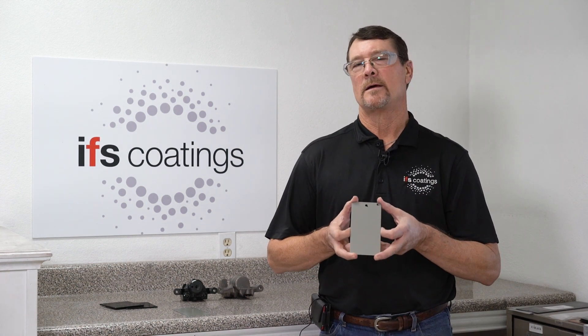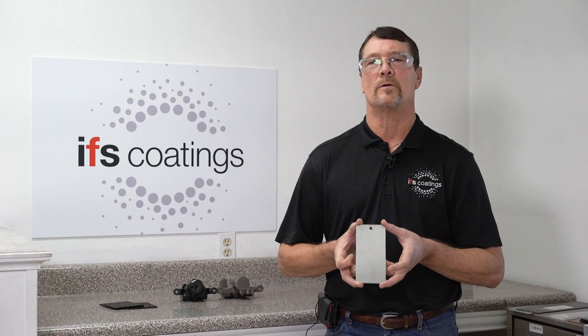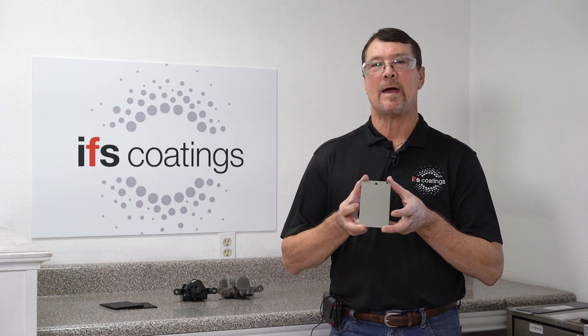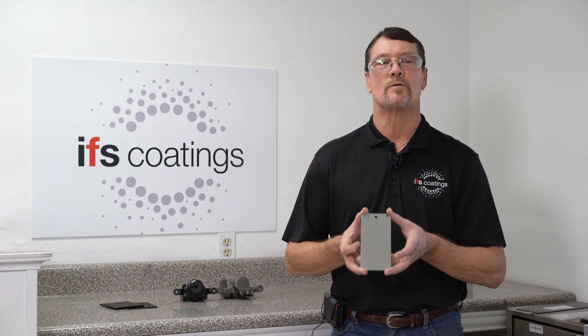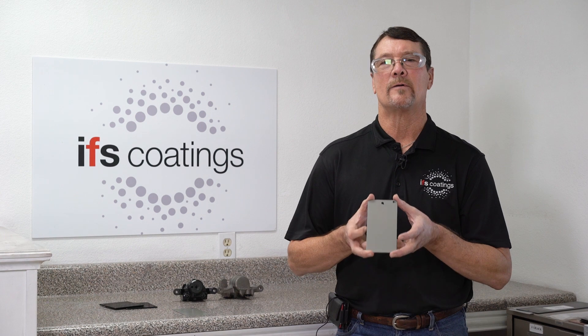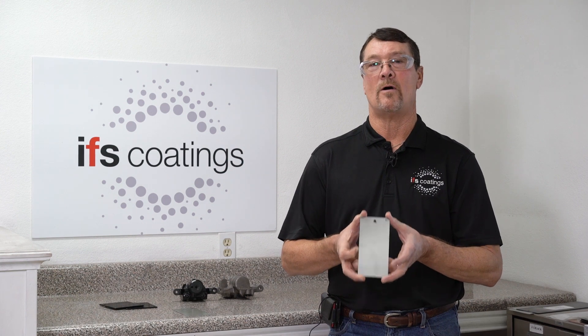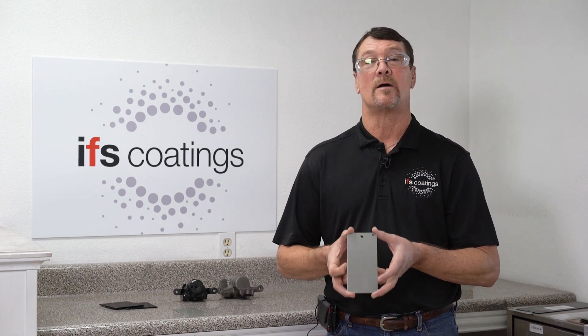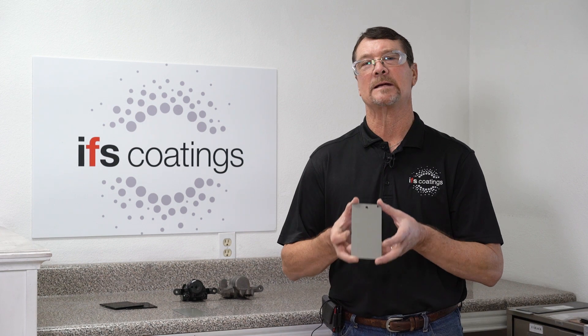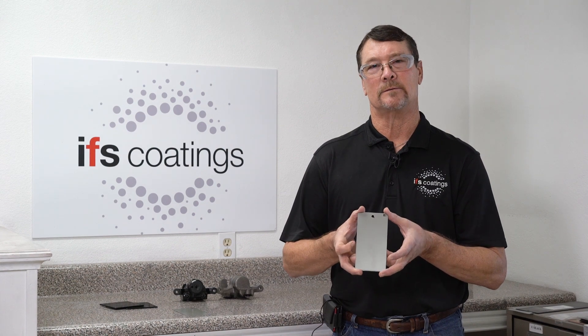Some of the ways you can guard against craters or help prevent fisheyes from forming on your parts: first, you want to be sure that you have good filtered air coming into your powder coating equipment. This is always a good point of preventive maintenance. Check your filters on your powder coating system, and if you ever see any oil or water building up on the inside, go back and check that your coalescing filters or any other filtration on your system is being maintained.